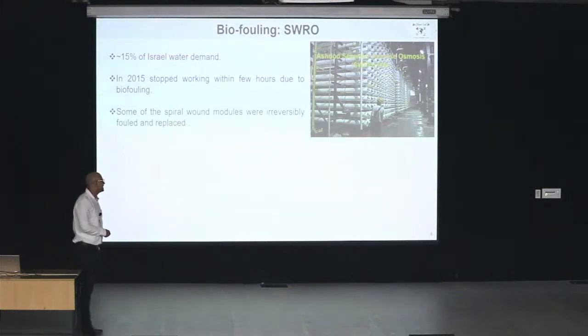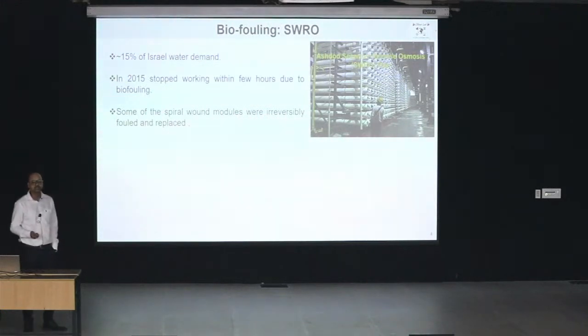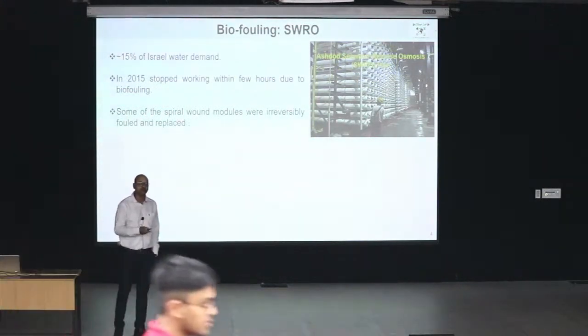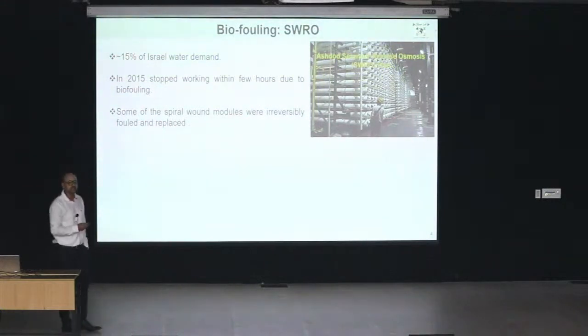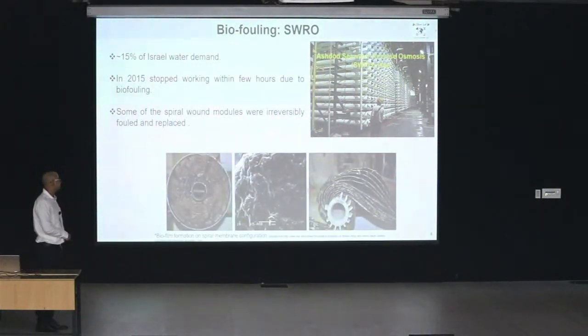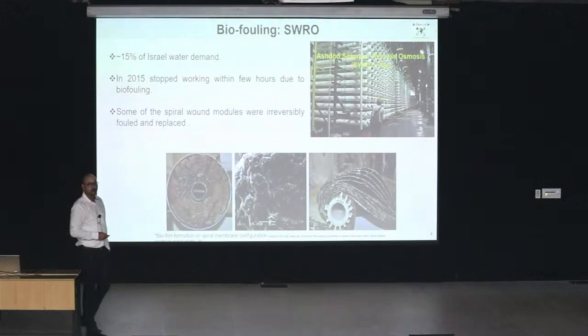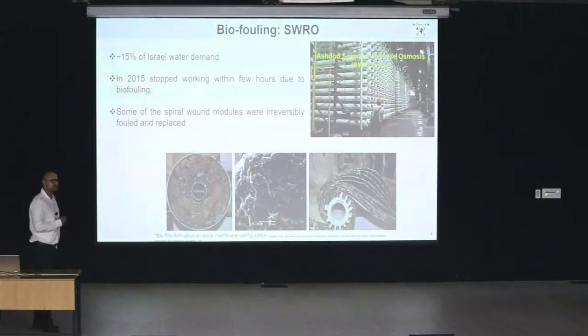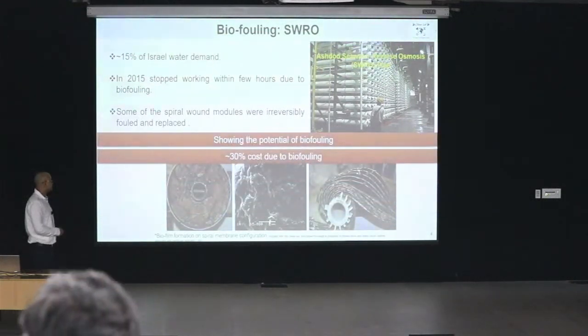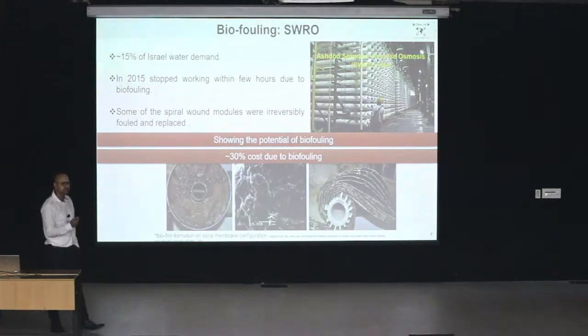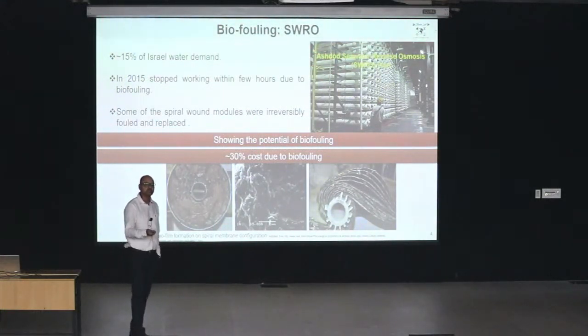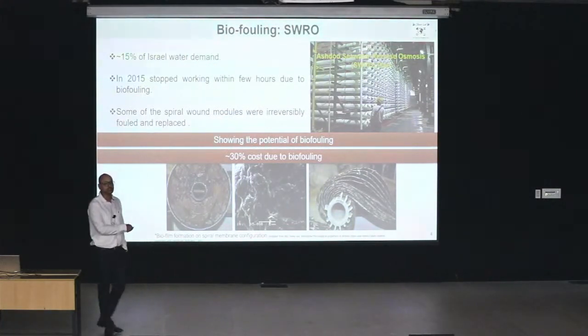For example, in Israel, they are pioneers in desalination technology and are running 5 big desalination plants, and many times their whole plant suffered because of biofouling problems, where within a few hours, if pre-treatment is not proper and microorganisms are able to reach the RO membrane, they can block the whole surface. And these are some representative SEM and digital images which show how severe this can be. In many cases, we have to replace the RO modules, which are quite expensive. So biofouling is reducing their life a lot. So it shows the overall potential, and at present, if you estimate the additional cost we are putting into desalination or wastewater treatment because of biofouling, it's 30% extra.